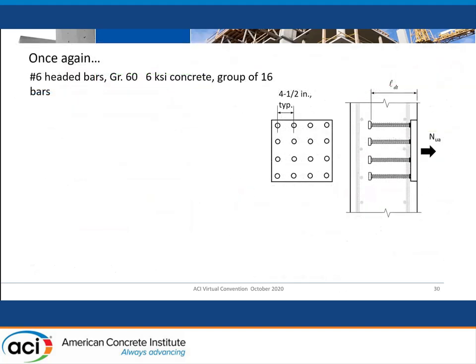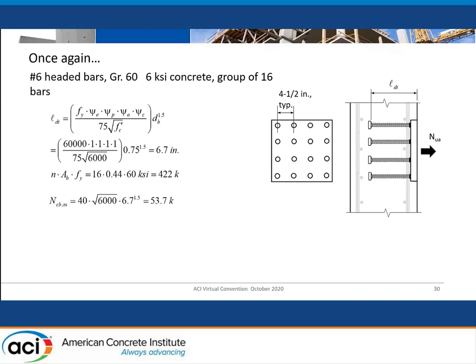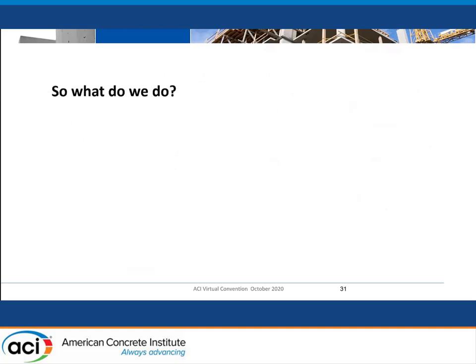Just to reinforce the point — this time with grade 60 bars and even more of them welded to a little plate — if I run the calculations I get nothing close to the capacity of all those bars at yield. I can do the same thing with hooked bars, and as we know now from the testing of Amit — because we didn't know that before he got started — you can even do the same thing with straight bars. He's using straight bars for most of those tests that don't have the same bond strength as standard lug bars — these were deformed wire anchors, what I think of as just dimpled wire. You would think, oh, not as much bond strength, it'll never happen. But indeed, if you stick enough force locally in the concrete, you will get the same failure mode.